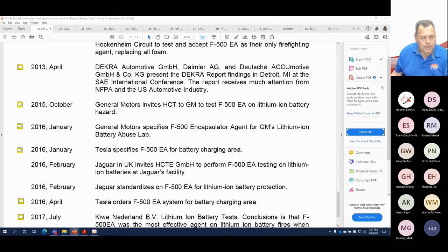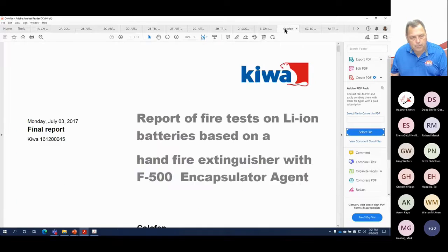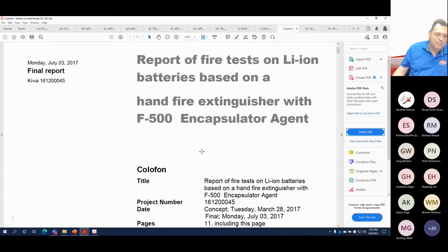I just want to show a little bit about what the encapsulator agent is doing. So on the lithium-ion battery, what's separating the F500EA from other items like foam and dry powder is, one, we're encapsulating the electrolyte, rendering it non-flammable and non-ignitable. And secondly, what we're doing is we're rapidly reducing the heat, and the heat is staying reduced to protect against burn back resistance and thermal runaway.